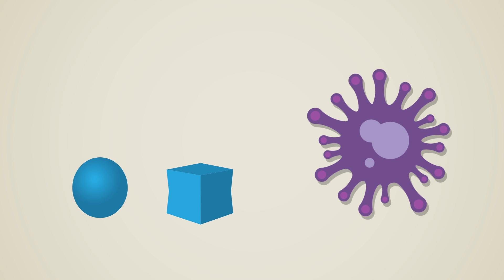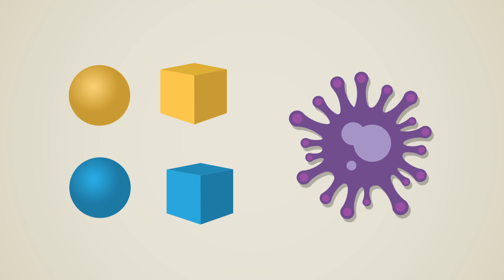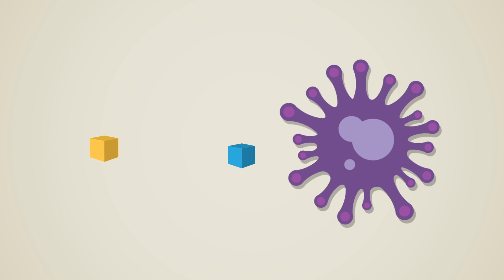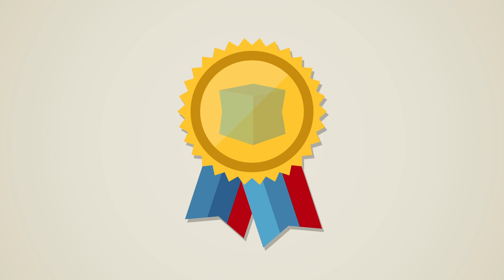In the test of being taken up by breast cancer cells, Kharlampieva found that the shape — not the hardness or squishiness — was key. The winners in this test were both of the cubes, whether solid or squishy. The flat sides appear to give better contact with the cancer cells, leading to more engulfment. Thus, the overall prize — drum roll please — goes to the squishy cube.